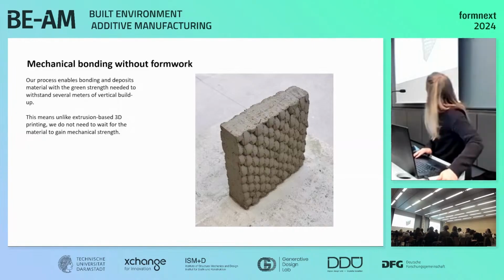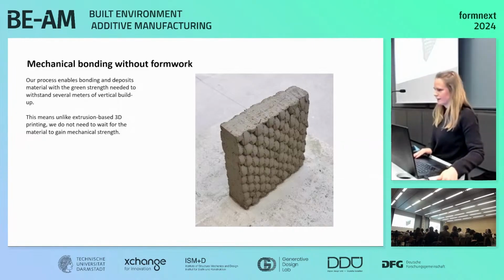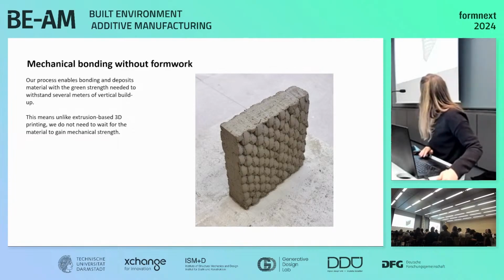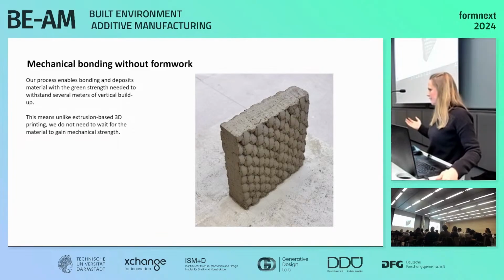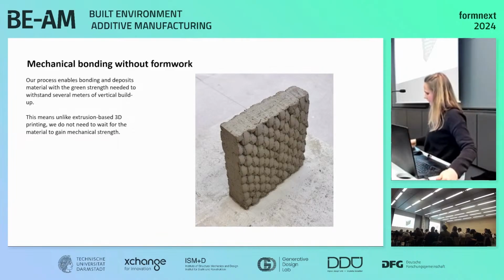So the main process benefit of this type of additive manufacturing, especially compared to extrusion-based manufacturing, is that we can enable mechanical bonding with materials that have extremely high yield stress, so greater than 28 kilopascals, and they basically wouldn't be able to be pumped. So they're kind of outside the range of delivery from a pumping system, probably even with rheological control.